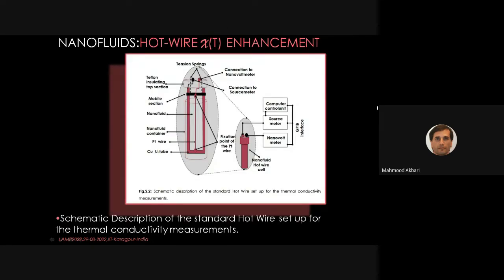Then we have to go for thermoconductivity measurements, colleagues. And here we go for the basic one. It takes time, certainly. It is time consuming relative to laser-based approaches, for example transient thermoreflectance and so on, where it takes some seconds and even less. And here it takes hours. But nonetheless, when we use the platinum hot wire based technique, we are capable to measure the thermoconductivity of the nanofluid at different concentrations, and also compare it to the host fluid itself. Next, please, Prof.